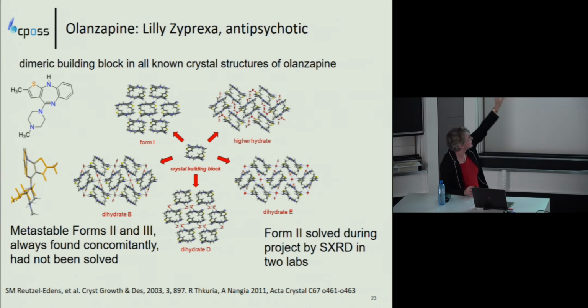They didn't know, despite Lilly having this under patent and doing an awful lot of work on the two forms, they'd been unable to crystallize forms 2 and 3 separately. They're always found as a mixture. But in our project, and also simultaneously in India, Nangia were able, out of the mixture of crystallites, to pull out a crystal that was big enough for current methods of solution from single crystals, giving the form 2 structure.